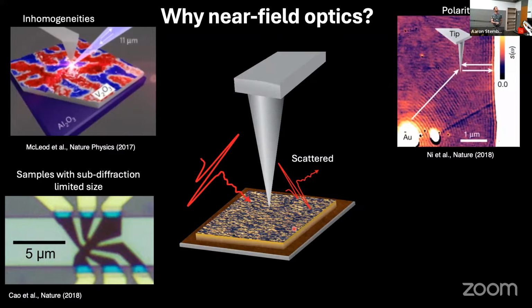So another reason is that this tip not only gives you spatial resolution, it also gives you the associated momentum to launch modes known as polaritons, where you have a hybrid of infrared radiation and collective modes in the material, which are dipole active. This can be plasmons. So this image shows plasmons propagating over tens of microns from a gold disk to the AFM tip. And you can see these oscillations in real space. And that is of interest for several reasons.